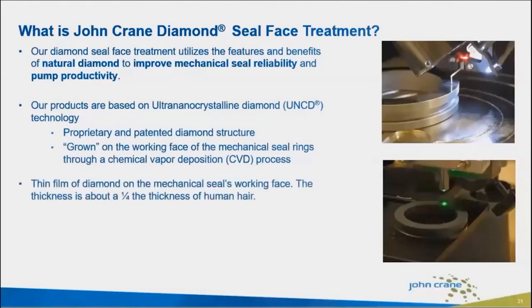The product itself is actually a thin film of diamond on the mechanical seal ring's working face. The thickness of the diamond film is about a quarter of the thickness of human hair. And this is really all the thickness that we need to capture the tremendous features and benefits of diamond for mechanical seals.